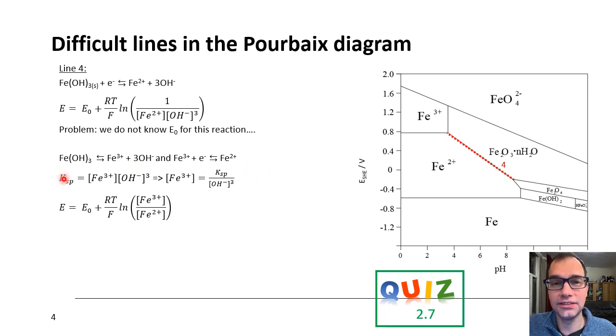Because for the first reaction, we can take the solubility product, as you can see here, as we did on the previous slide, and we can recalculate that the iron 3 concentration is the solubility product divided by the OH minus concentration to the power 3. And the other reaction we have also seen on the previous slide, and we say, hey, this has a potential E is E0 plus RT/F ln of iron 3 divided by iron 2. And of this reaction, we do know the standard electrode potential. So now we can take the next steps here.